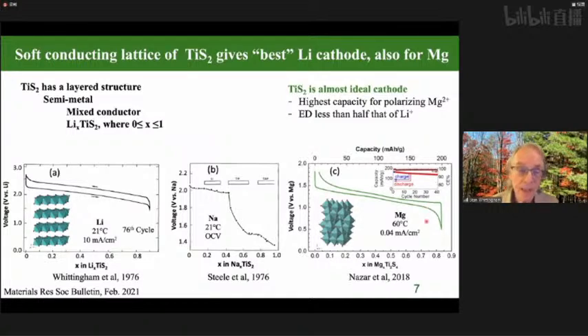The challenge here, divalent ions don't diffuse very fast. So this data was collected at 60 degrees centigrade, and the current density is only 0.04 milliamps. So much, much slower than lithium. The other key feature to note here is the voltage is about 1.2 volts, so almost a volt lower than lithium. And this is why magnesium cells are not going to be commercially viable. They've got a much lower voltage, much lower rate capability, and therefore much lower energy density. But we really need to understand them to better understand how diffusion occurs in these materials. And there's ongoing work on calcium, which is a bit bigger, so might diffuse somewhat better.